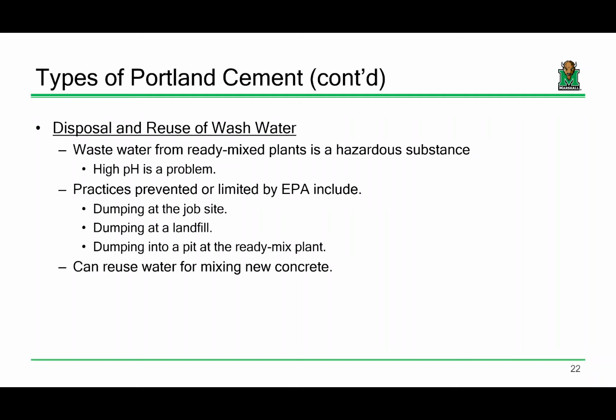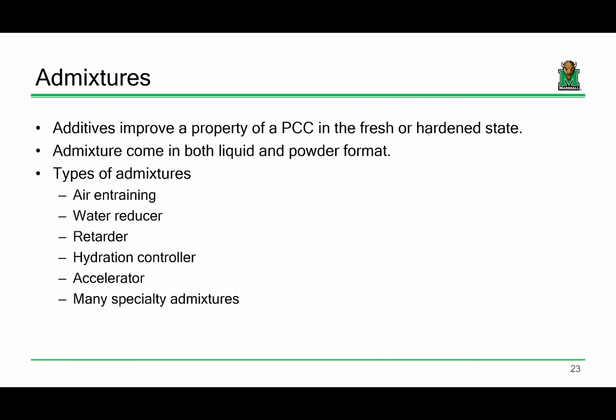The one thing I will say, in terms of an environmental issue, is that the wash water from the ready-mix plant, where they're producing cement and concrete and whatnot, is actually pretty environmentally hazardous because it's got a ridiculously high pH. It's a very alkaline water, and that's not very good. And so the EPA does have limitations on what you can do with that wash water, so you're prevented from dumping it at a landfill or at a job site. You can reuse that water for mixing new concrete, that's fine, but you can't just dump it. It's a really, really high pH water, and that's a bit of an issue.